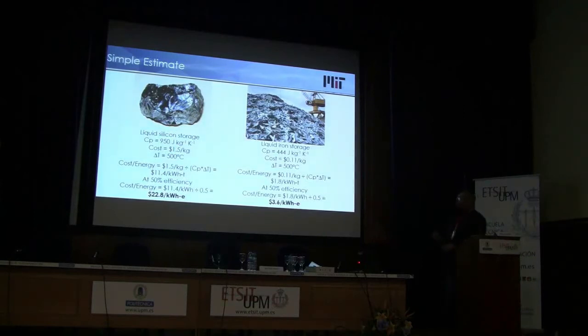If you want to store, for example, something like metallurgical grade silicon, the cost, swinging it over, let's say, a 500 degree C delta T, comes out around $23 per kilowatt hour electric. This is assuming a 50% nominal efficiency for the heat engine. And so this initial cost number is attractive by comparison to lithium-ion batteries. This is roughly speaking a factor of 10 or more cheaper.